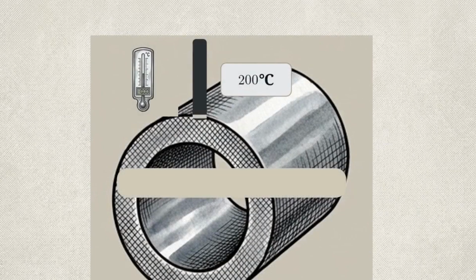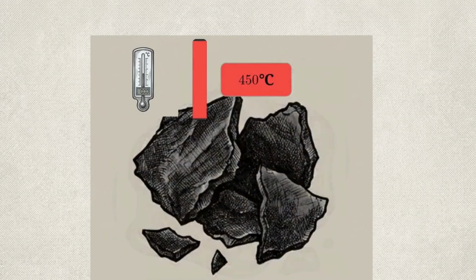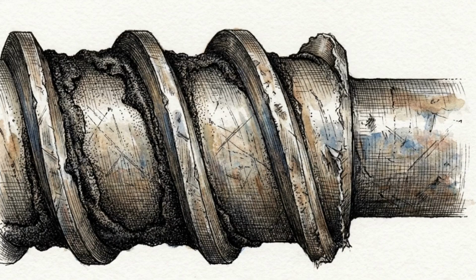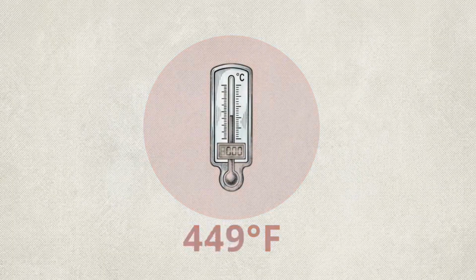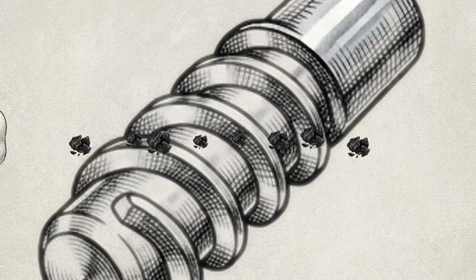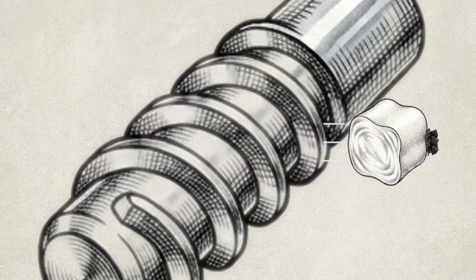When operators treat these elastomers like rigid plastics, the first instinct is often to increase the heat. But instead of melting the residue away, the excess temperature carbonizes it. Low-temperature mechanical purging solves this by dropping the heat and relying entirely on physical friction. It clears the barrel completely without requiring a manual screw pull.